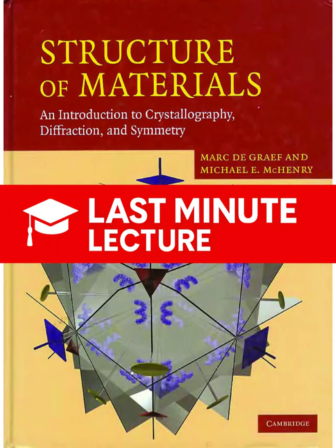The non-crystalline and nanomaterials. And we start with the most common amorphous silicate, glass. Amorphous silica, or SiO2, is globally important, and the structure of glass is explained conceptually by Zachariasen's continuous random network model, the CRN model, from back in 1932. What does the CRN model say about the structure of glass? The key idea is local order, but no long-range order. The preferred local tetrahedral coordination of silicon surrounded by 4 oxygen atoms is perfectly maintained. The tetrahedra still share vertices, just like in quartz, but the structure lacks long-range translational periodicity. There's no repeating unit cell.